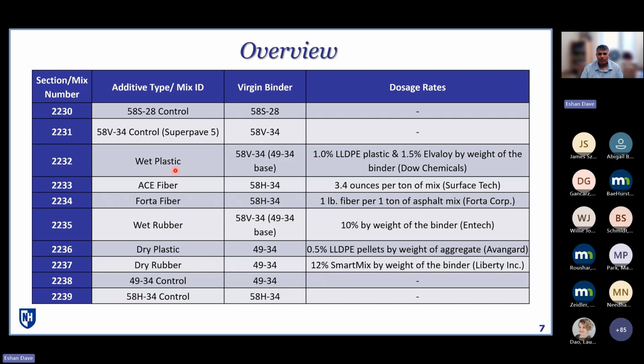So the wet plastic is essentially using a linear low density polyethylene plastic at 1% dosage together with Elvaloy to make the wet plastic. The two aramid fibers, one is the ACE fiber by Surface Tech, and you can see the dosage rate 3.4 ounces per ton. With Forta fiber, it's 1 pound per ton of asphalt mixture. So those are the dosage rates on those. Again, dosages were primarily based off of the manufacturer's recommendations.